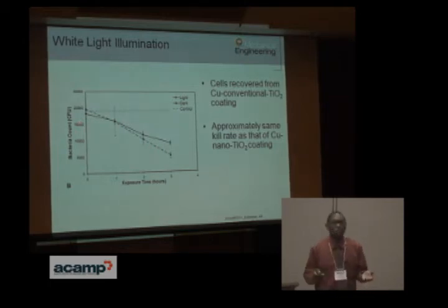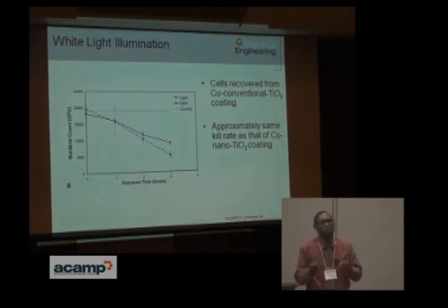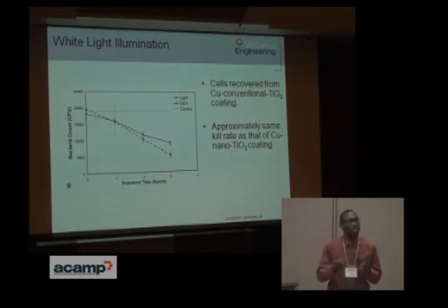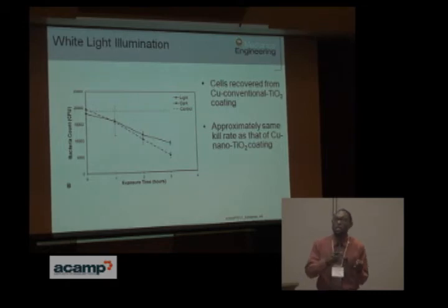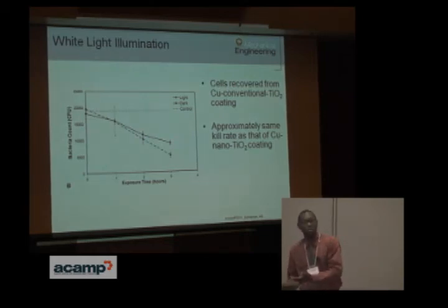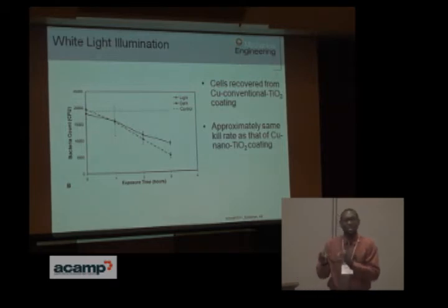Now, one may be asking, well, why not just go with the cheaper conventional TiO2 and be done with it? You know, I may have to pay more money for nano. But you should understand that from our work, not shown here, the nano TiO2 coatings tend to have lower porosity, so then you get lower liquid penetration of these bacterial solutions. The nano TiO2 coating has high hardness, which is indicative of improved wear resistance. And the cost is not significantly different, but you do get some benefits with the nano-based coatings.